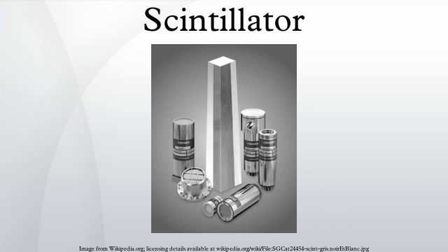Scintillation counters are usually not ideal for the detection of heavy ions for three reasons. The very high ionizing power of heavy ions induces quenching effects, which result in a reduced light output. For example, for equal energies, a proton will produce 1/4 to 1/2 the light of an electron, while alphas will produce only about 1/10 the light.